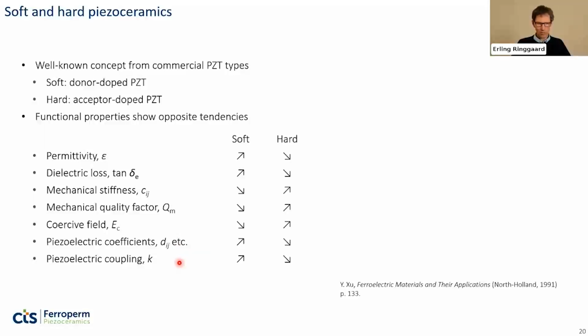And what about hard? Well, it's very simple. All the arrows point in the opposite direction, so all the tendencies are in the opposite direction. For example, normally you would appreciate having a lower dielectric loss, which you get with a hard PZT. So when I stress that it's a donor and acceptor doped PZT, the point is that you cannot really say that in order to get it for the lead-free ceramics, you need to use a donor type dopant or an acceptor type dopant. It's not generally as simple as that. Sometimes you need to use other strategies than simple donor and acceptor doping.